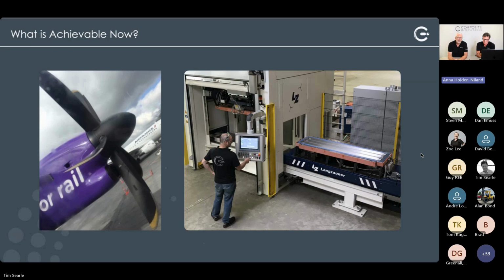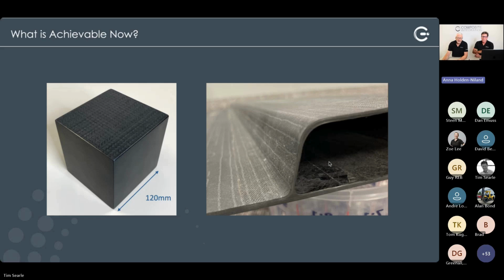Part of all that cell, we do a lot of data acquisition, and remotely we can draw in that data in real time, and we do analysis to help continue to optimize that process and deal with any issues that come up. So this cell is one of 6 that's installed in one factory in Europe, and currently producing more than 10,000 really high quality, high VF, low void content components every single week. So more than 10,000 a week. So we've been working very hard on quality, and without that, the other 3 requirements that we've mentioned become a bit questionable.